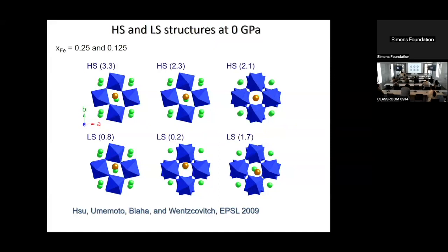Across the high spin to low spin state change, the gap opens from 1 to 3. That means infrared light can go through, so conduction through radiation is more important, and that damps the vigor of the convection in the lower mantle. So that is the implication. So this is an important problem too, figuring out what happens with the optical properties across the spectrum. That's a cool problem, very cool problem.